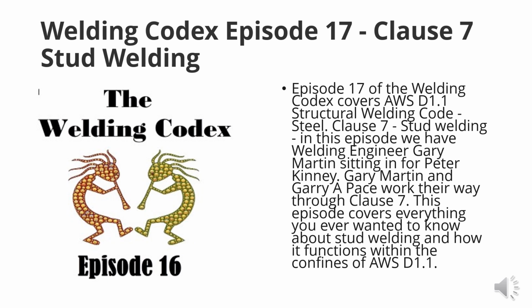7.6.4 is the number of specimens. So it tells you 10 specimens shall be welded consecutively using recommended procedure and setting for each diameter position and surface geometry. And tests required. 10 specimens shall be tested using one or more of the following methods of bending, torquing, or tensioning. Kind of jumped through some stuff there, Garry. What do you think? Yeah, and again, we're talking about the procedure qualification for the application of studs, not the qualification of the stud bases themselves, which is normally done by the manufacturer. That is a different type of testing and quantity completely.